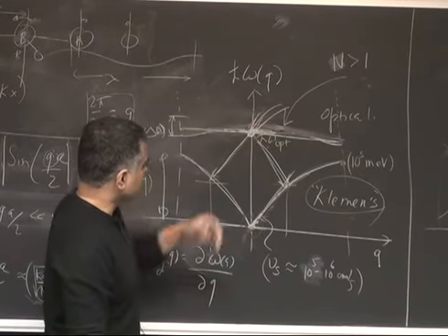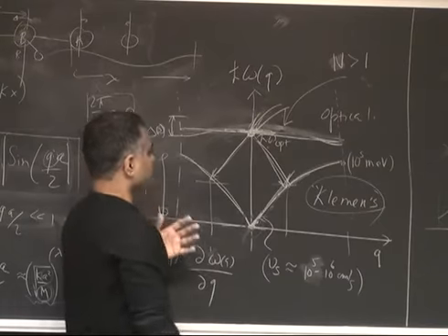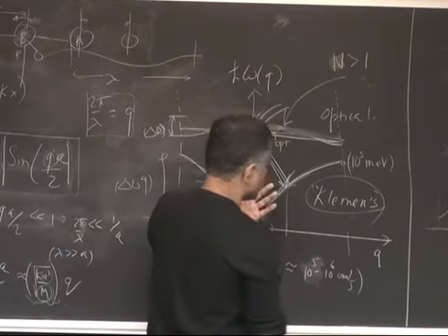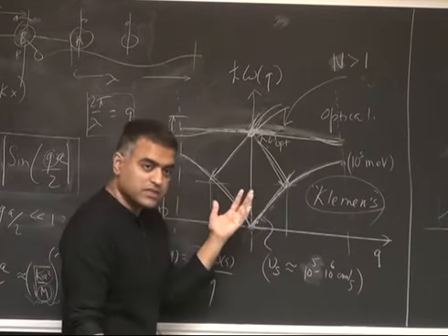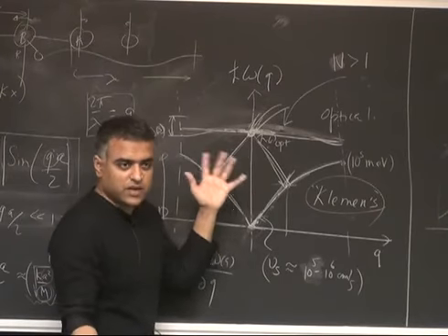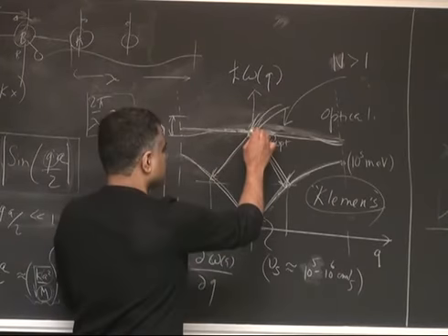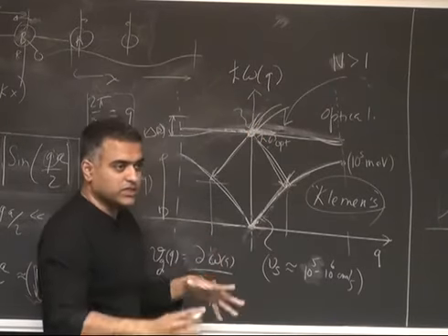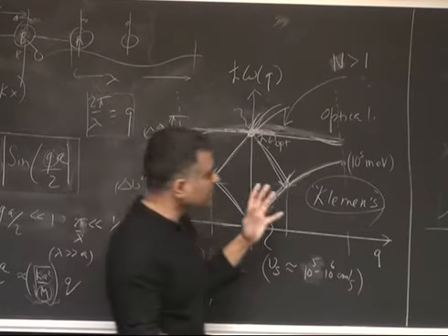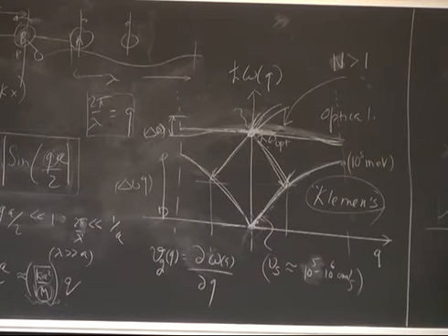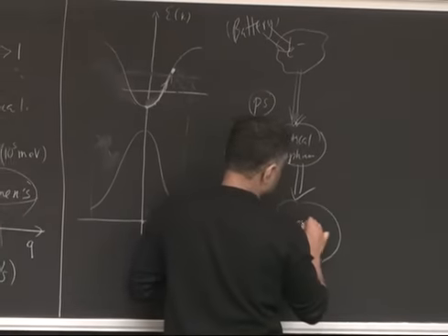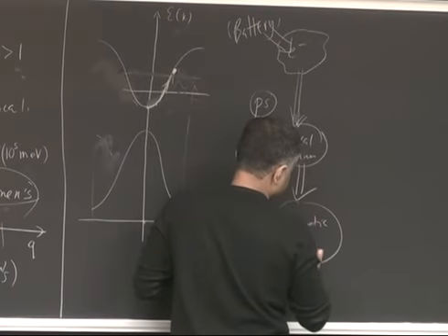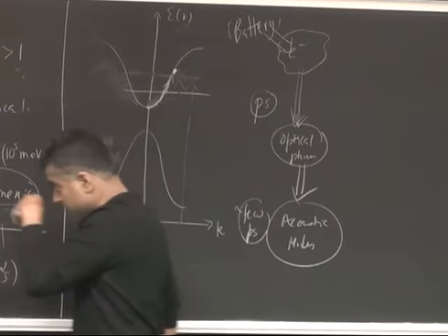The time scale for a typical semiconductor would be a few picoseconds. Sometimes about a picosecond, but a couple of picoseconds is how long it takes after you excite an optical phonon mode for it to decay into acoustic modes. So from optical modes, you're going, in a few picoseconds, into acoustic modes of phonons. That's where the energy goes.